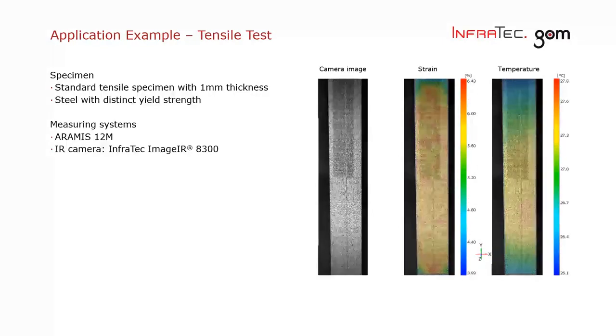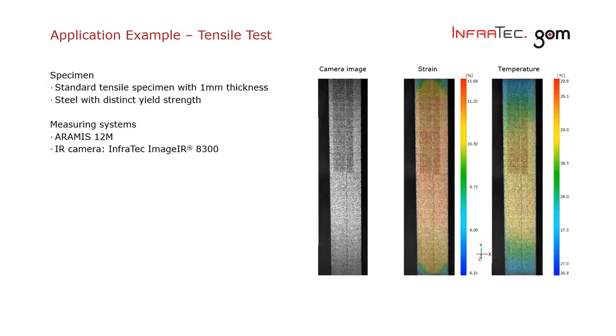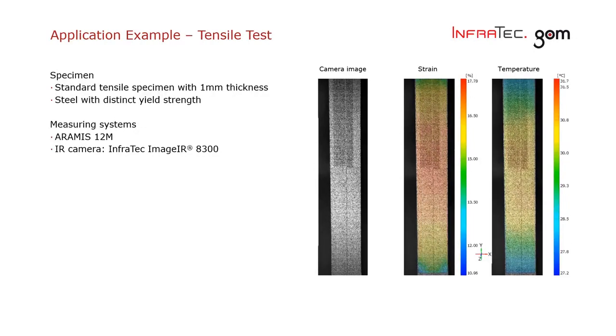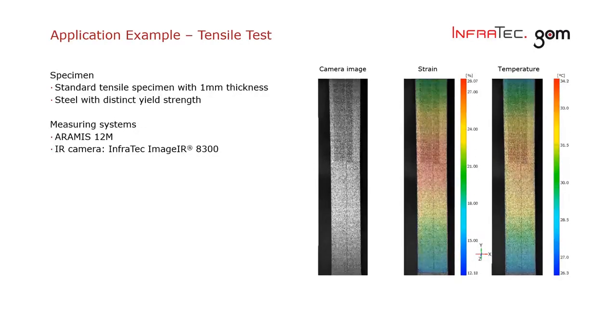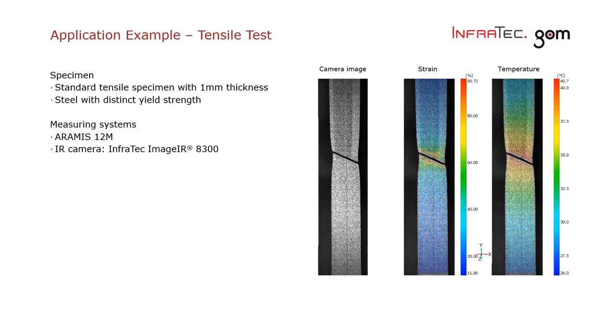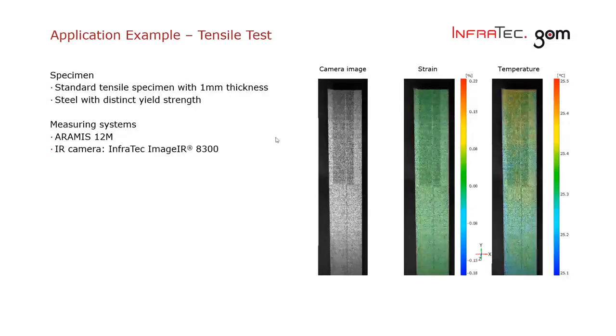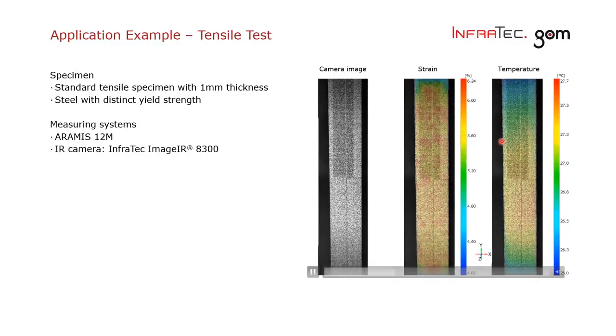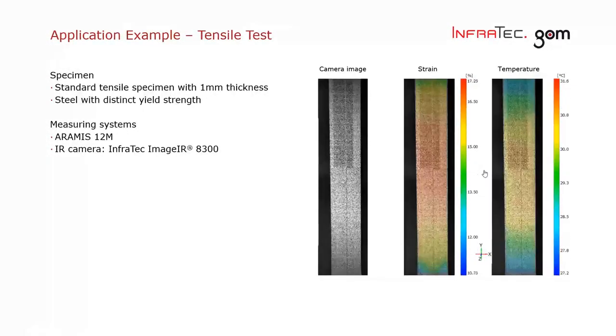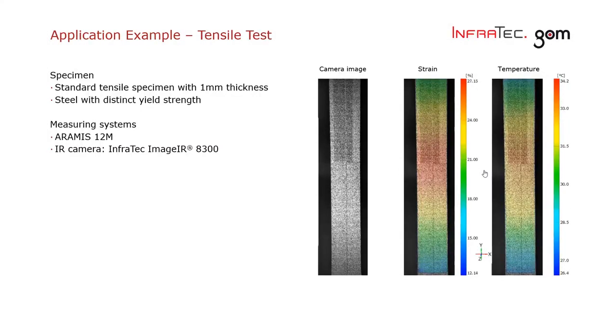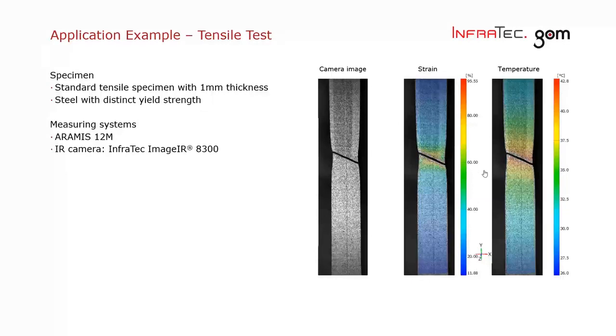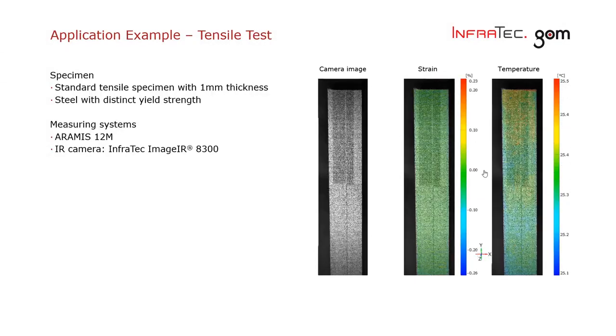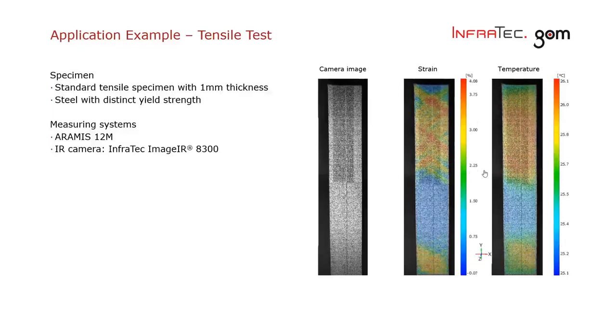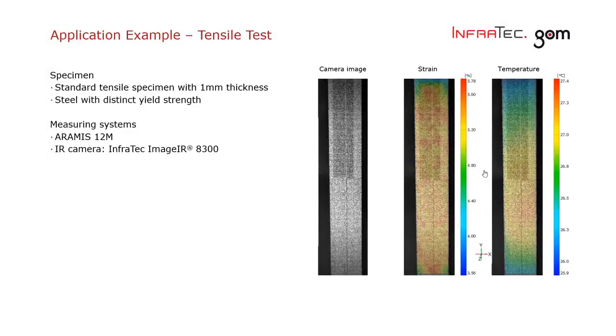Having a little closer look on the measurement results over here, in the beginning of the test is the elastic phase. The video will start in a few seconds again. We will see some temperature changing, which is going to happen in the elastic range, which is starting now. You see some changes happening due to the generation of the Lüders bands in this area over here. Then the specimen is going through the standard deformation happening before the specimen is starting to neck and fail, where also the temperature distribution starts to localize due to the high load on these local areas.